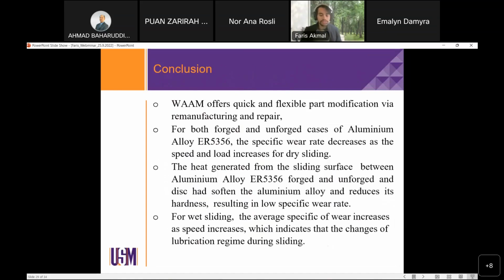So we go straight to the conclusions. Okay, WAAM offers quick and flexible part modification via remanufacturing and repair. For both forged and unforged cases of aluminum alloy ER5356, the specific wear rate decreases as speed and load increase for dry sliding. This is because the heat generated from the sliding surface between aluminum alloy ER5356, forged and unforged, has softened the aluminum alloy and reduced its hardness, resulting in a low specific wear rate.